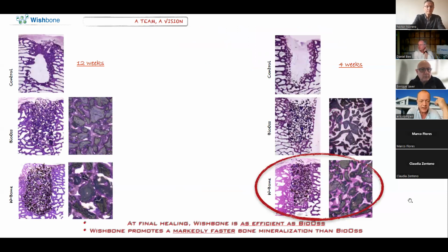This is still in sheep, not in dogs, and that is the difference that we have between BioOss and Wishbone at 12 weeks. BioOss is excellent, and the Wishbone material is also excellent, as you can see on the left side. On the right side, you see 4 weeks, and at 4 weeks between BioOss and Wishbone, we have a very significant difference. That is, the mineralization between the particles is significantly higher with Wishbone as compared to BioOss. Next slide.